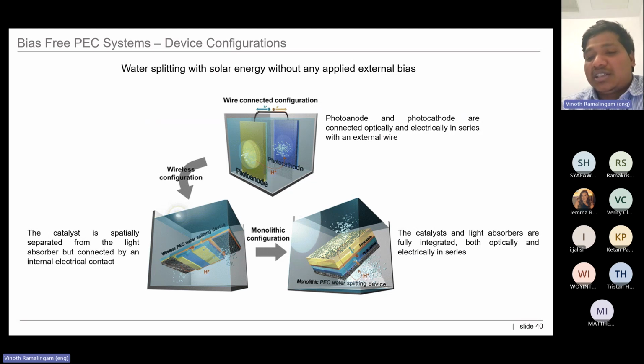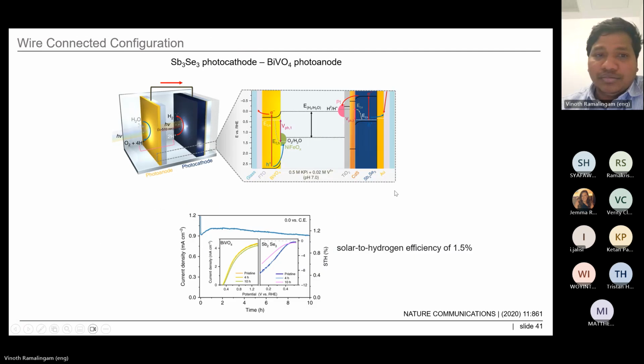The catalyst materials and light absorber, it's called a fully integrated device. In that case, you can perform PEC reactions on the device. This is an example of wire connected configuration from literature, where they used antimony selenide photocathode and BiVO4 for photoanodes, where they wired two different devices and were able to achieve a solar hydrogen efficiency of 1.5%.